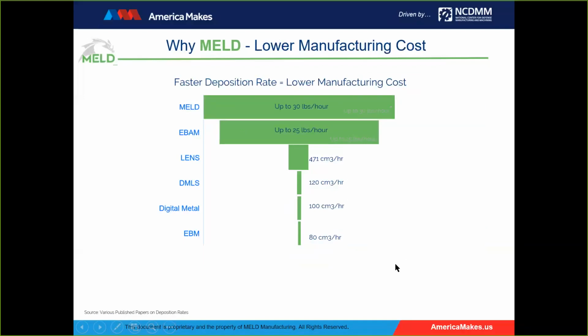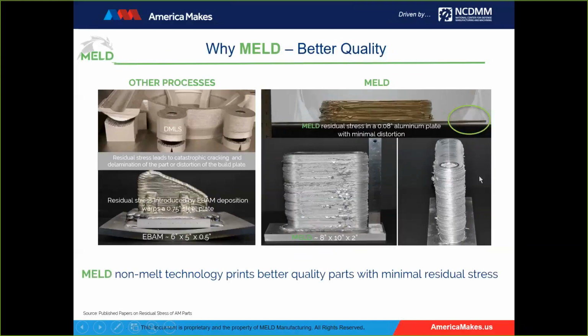Fast deposition rate. I mentioned 30 pounds an hour. Here's just a visual on deposition rates of other technologies. I put my sources on the left-hand side, so I'm reasonably accurate with all my data. Residual stress. Well, we're solid state. You shouldn't expect there to be a lot of residual stress, so I picked out a horrific powder bed example, so it doesn't really count.